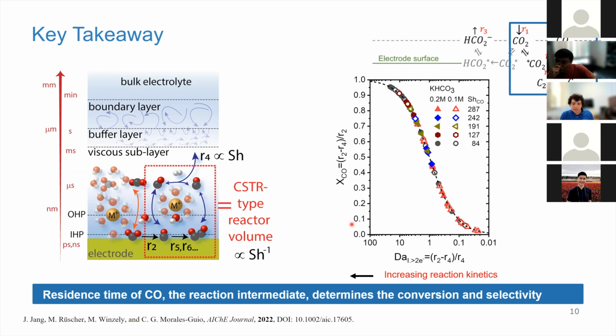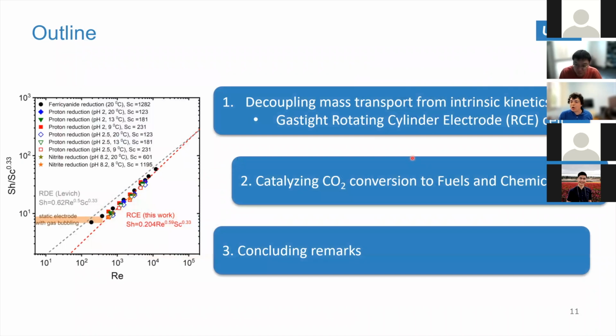Okay. So these are experimental results for CO2 reduction in different electrolytes, so different bulk pH, different conditions. And again, everything just collapsed on the same line for copper, indicating that the intrinsic kinetics, the K, is the same. It's just that by changing hydrodynamics in the cell, you see different conversions and different product distributions. So how do we get there?